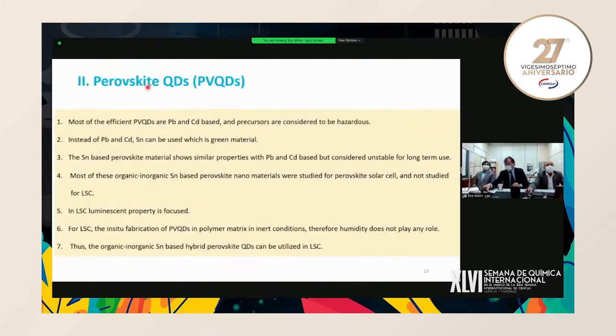So out of quantum dots, we'll discuss about perovskite quantum dots. So nowadays, perovskite quantum dots have been researched by many researchers around the world. So most of the perovskite quantum dots are lead and cadmium based. And these lead and cadmium are considered to be hazardous. So if we replace this lead and cadmium by some green materials like tin, so we can have some green perovskite materials, which will be clean and also environmentally friendly. The tin-based perovskite material shows similar properties with lead and cadmium-based, but is considered unstable for long-term use.